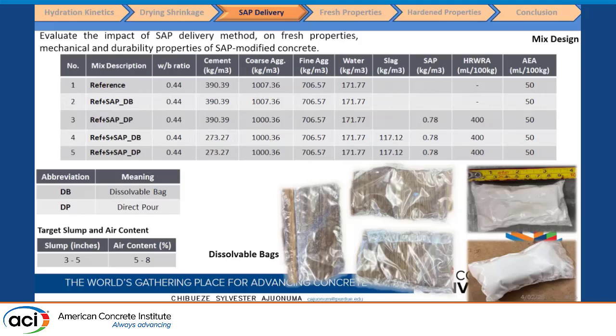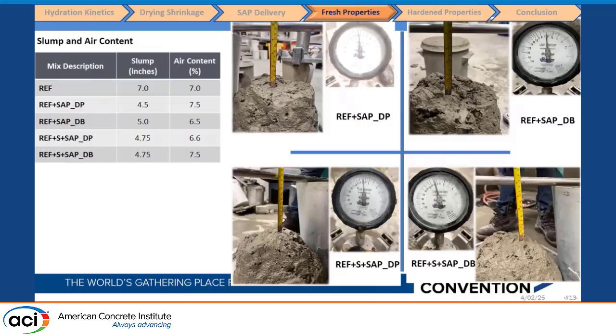From our design, our target slump was between 3 to 5 inches, and air content was between 5 to 8%. For the laboratory experiments, for the mixtures without SAP, we didn't use a high range water reducer, but for mixtures with SAP, in order to improve the workability, we added a high range water reducer at 400 mL per 100 kg. And we also used an air entraining admixture to be able to meet our target air content of 5 to 8%.